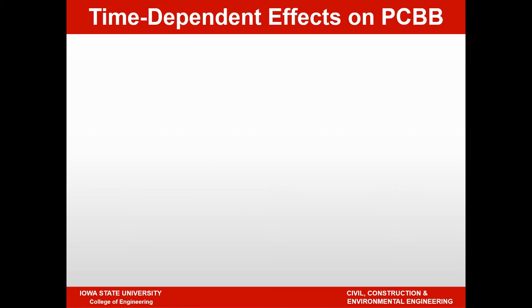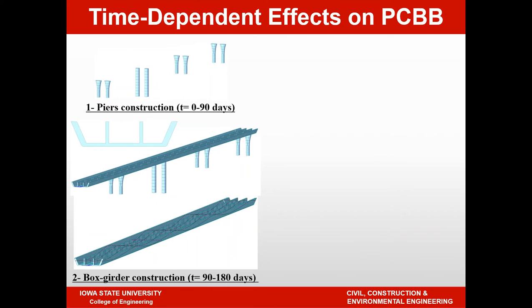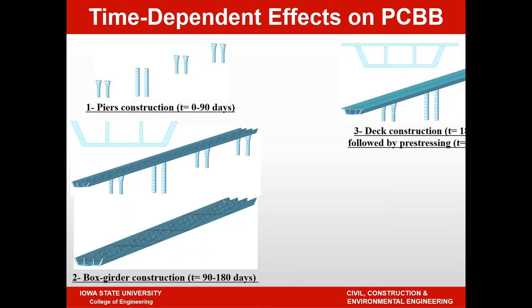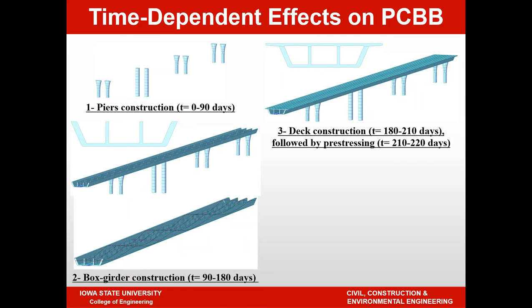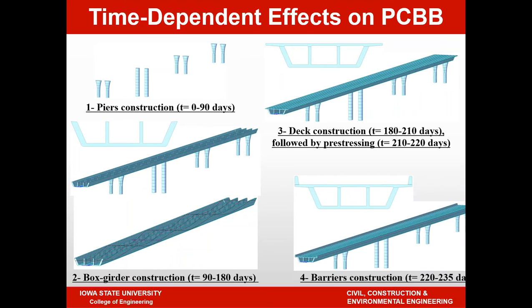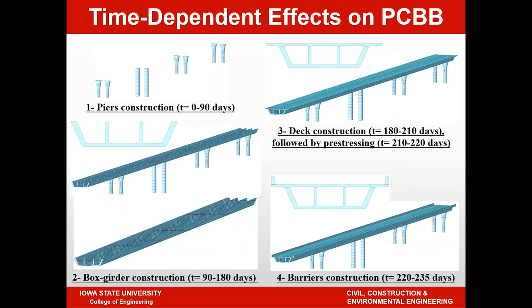So this figure shows the pier construction. Typically, we assumed in this case, with input from the Caltrans Technical Advisory Committee, that the substructure construction will take place from 0 to 90 days. Then you add the superstructure from T equals 90 to 180 days, followed by deck construction from 180 to 210 days, followed by pre-stressing in the superstructure between 210 to 220 days, and finally the barrier construction was completed from time 220 to 235. So this is when you complete the structures.